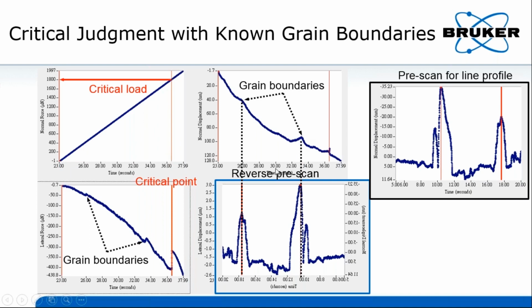Since we have the pre-scan data of the line profile of the scratch path, and the direction of pre-scan is opposite to the direction of the scratch, all we have to do is to use the reverse of the line scan profile for checking the locations of the grain boundaries.